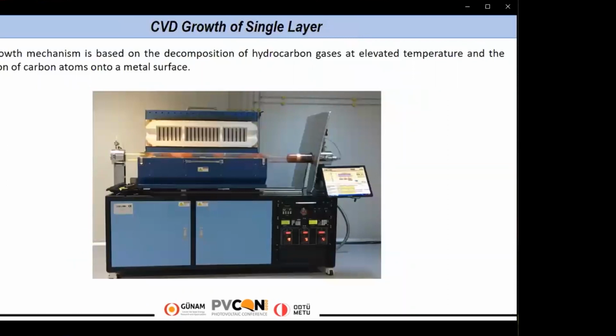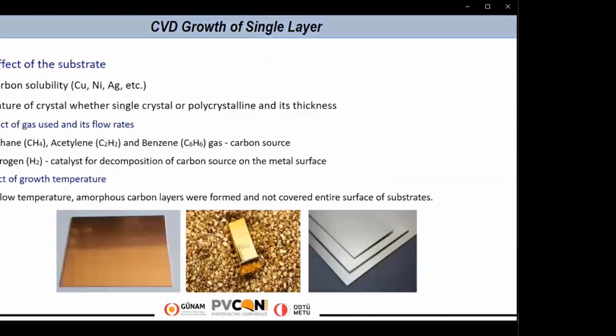There are a few methods for graphene synthesis. The chemical vapor deposition method, CVD, is one of the most popular methods because of large-scale and homogeneous graphene synthesis. The growth mechanism in CVD is based on the decomposition of hydrocarbon gases at elevated temperature and the diffusion of carbon atoms onto the metal surface. Many parameters are important for graphene synthesis: substrate, flow rates, and temperature. Even your gas purity can affect your graphene quality seriously. So most parameters should be optimized for large-scale graphene synthesis.